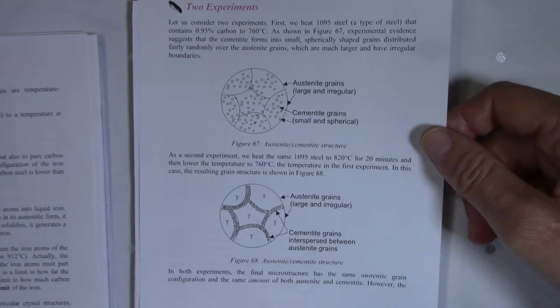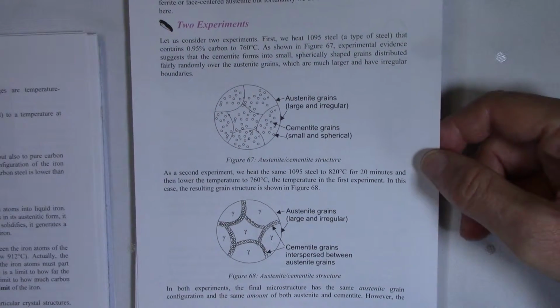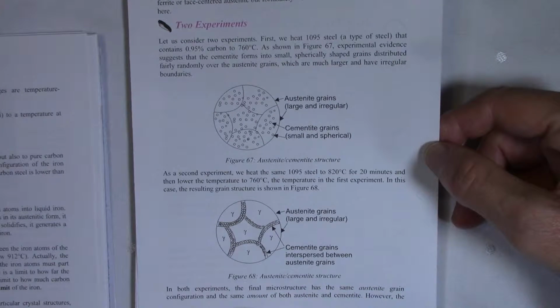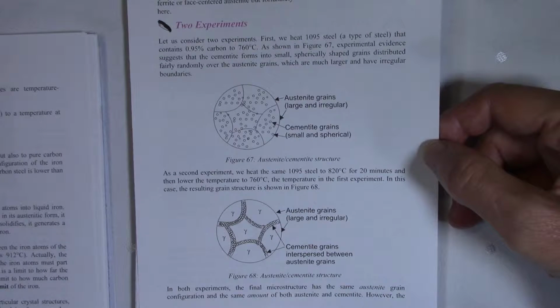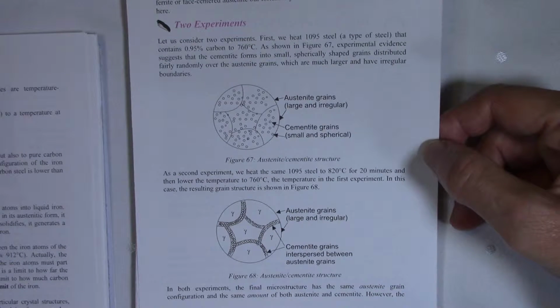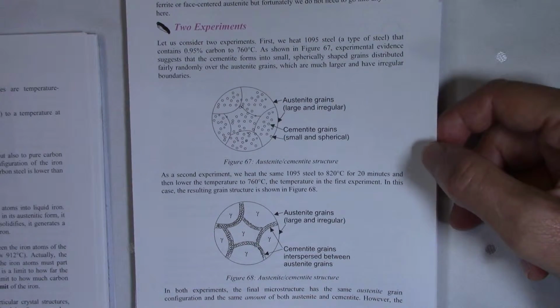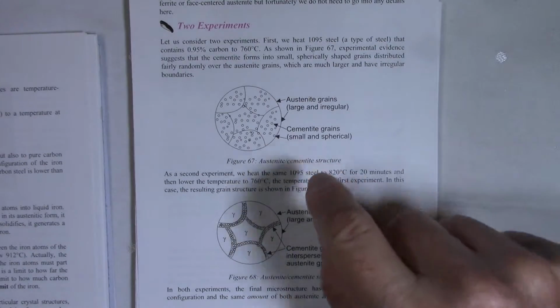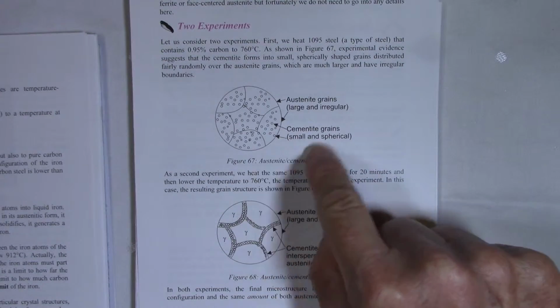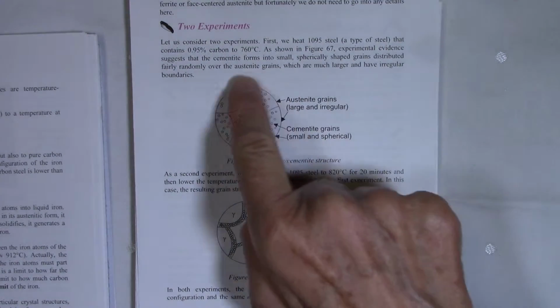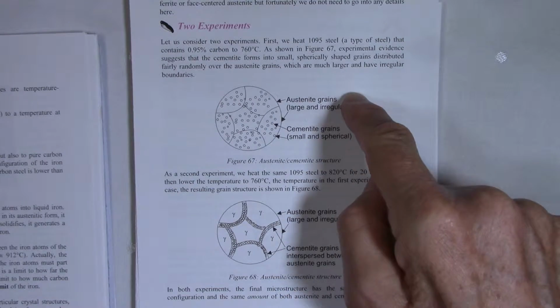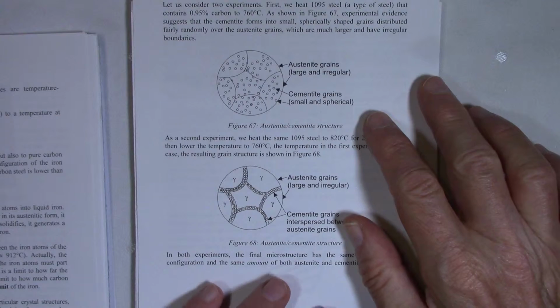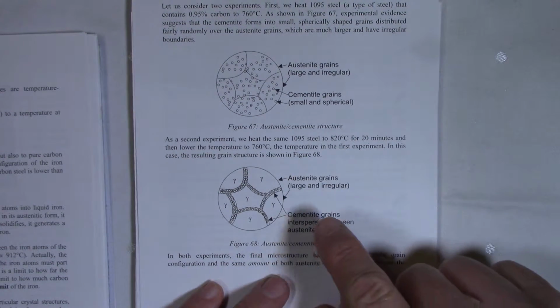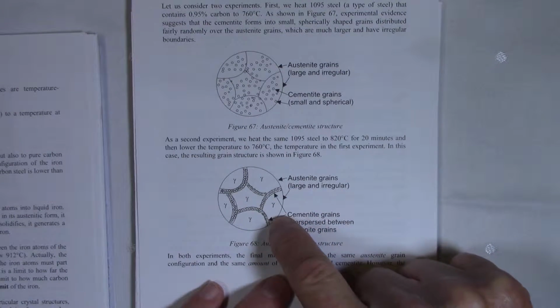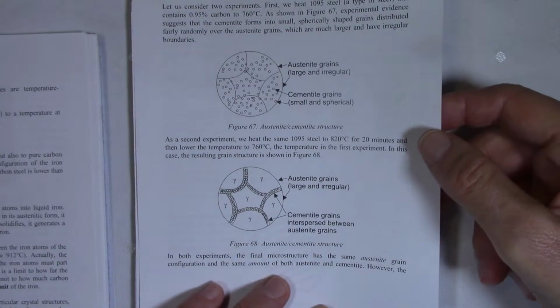Then I discussed two experiments which show what happens if you heat a type of steel, 1095, to 760 degrees centigrade, or if you heat it to 820 degrees centigrade for 20 minutes and then drop it down to 760 degrees centigrade. There's a big difference in the final result. In the first case, the distribution of cementite grains, which are small, is pretty uniform among the larger austenite grains. But in the second case, where we went up to 820 degrees centigrade, the cementite grains formed or distributed in the boundaries between the austenite grains.